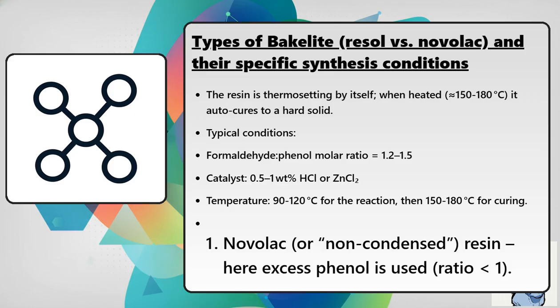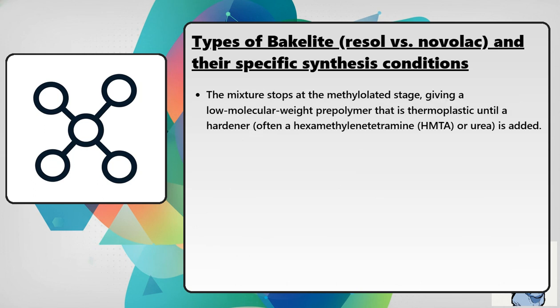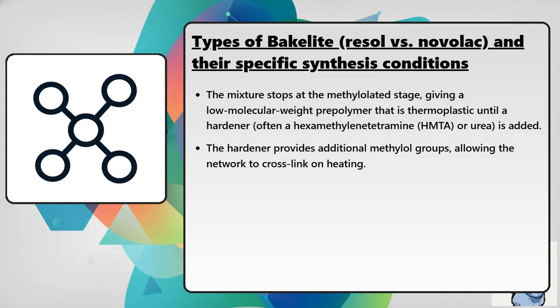Novolac or non-condensed resin, here excess phenol is used, ratio less than 1. The mixture stops at the methylolated stage, giving a low molecular weight prepolymer that is thermoplastic until a hardener, often hexamethylenetetramine, HMTA, or urea, is added. The hardener provides additional methylol groups, allowing the network to cross-link on heating.